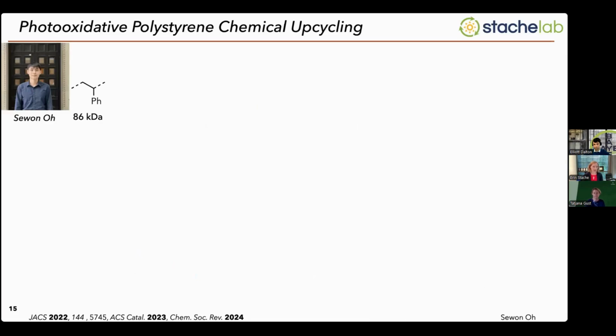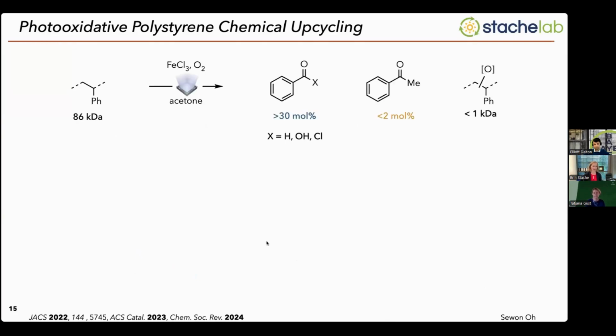And so all of this work was carried out by one of my first graduate students, Sewon. What he first did is he synthesized some polystyrene in the lab, so standard radical polymerization, and then he subjected it to iron trichloride, oxygen, and broad spectrum white light. And what he found is that you could selectively break down polystyrene into benzoic acid.